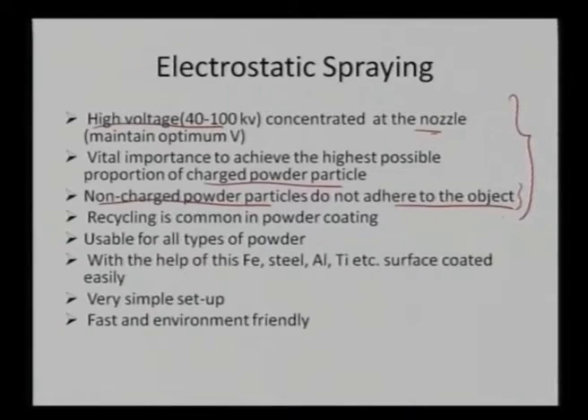We will come back to it. It is more like a coating technique, the way we utilize it for spraying. So, we have a particular charged entity. We basically throw the powder at a particular substrate, which is kept at a lower or ground potential to complete the overall circuit, and the charge on the powder particles is utilized for their travel from an electrostatic gun to the substrate. Later on, we can do some sort of curing to keep those powder particles intact, so that they can get fused together.